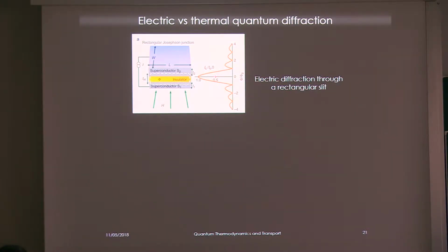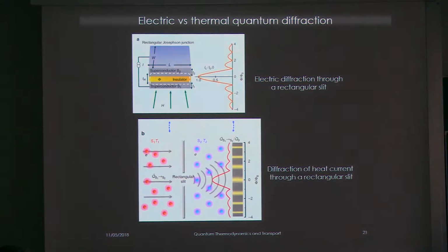Then, as happened with the electric Josephson effect, we wanted to probe electric versus thermal quantum diffraction. Okay, so probably many of you know that in an extended Josephson junction with an in-plane magnetic field, it's possible to observe a diffraction pattern, a beating pattern, in the critical current behavior. Okay, this is because the phase accumulates and then creates a sort of interference with itself. And the idea was to show that also for a thermal system, so a thermally biased extended Josephson junction, one could have a sort of diffraction of thermal current in the system.